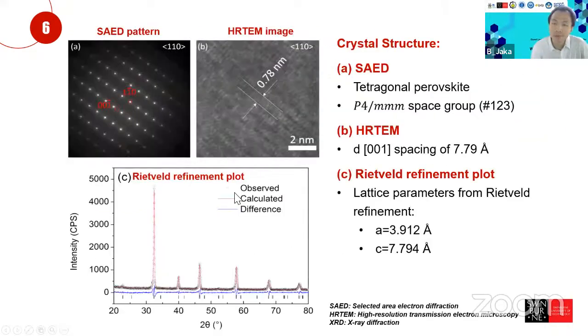Okay, so in all the research on cathodes for solid oxide fuel cells, normally we would like to know the crystal structure of these particular materials. To do this, we ask for an electron microscope to do a selected area electron diffraction pattern and a high resolution TEM image, and then also complemented by the powder X-ray diffraction pattern. Okay, so based on the SAED pattern, which is done along the axis of 110 in